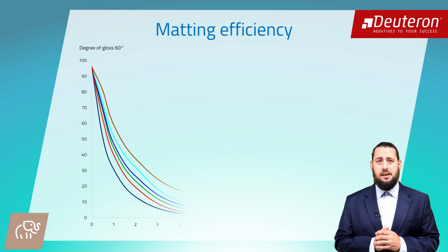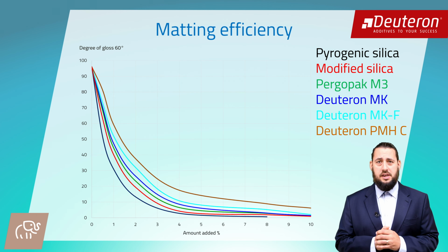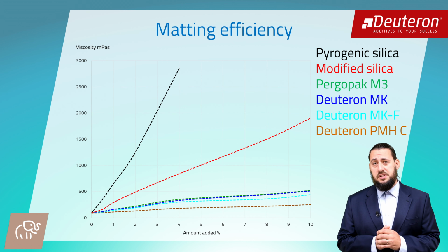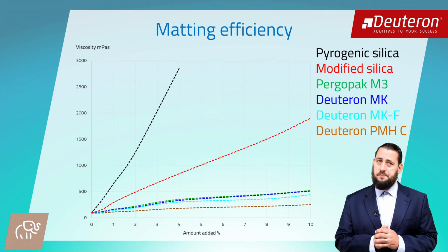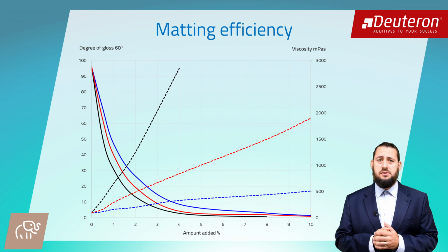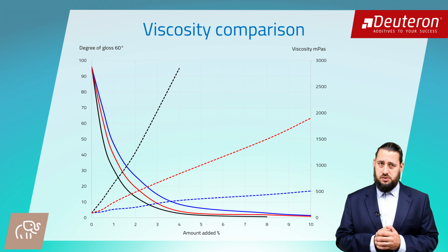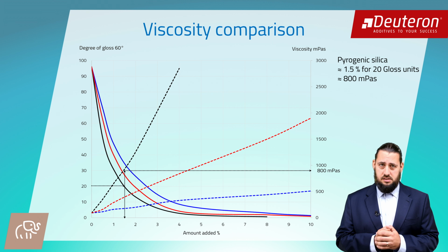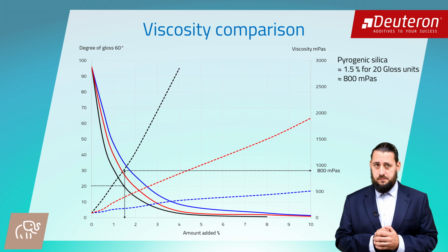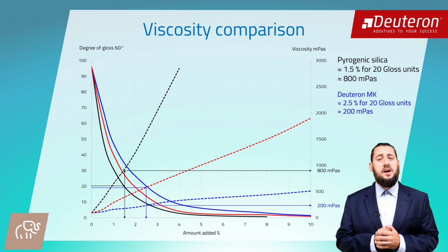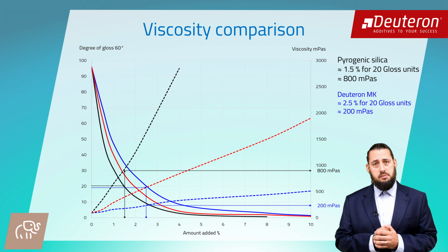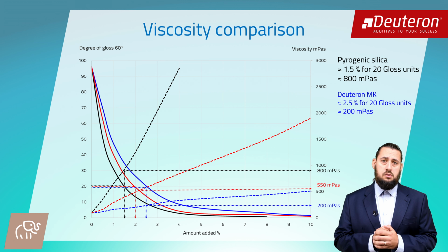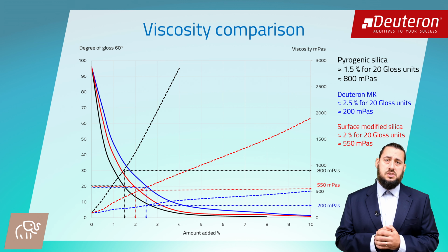The matting efficiency is high, but compared with silicas, the needed amount of organic matting agents can be higher. If we compare the resulting viscosities, the significant increase due to the silicas is clear. In this graph, we compare the different amounts of matting agents needed for 20 gloss units. 1.5% of pyrogenic silica added to our testing lacquer leads to 800 millipascal seconds. Deuteron MK requires 2.5%, but only leads to 200 millipascal seconds. An amount of 2% modified silica creates a viscosity of 550 millipascal seconds.